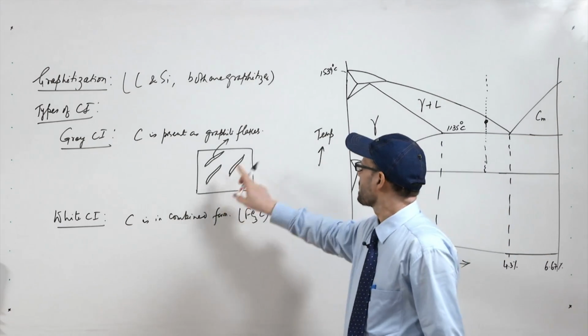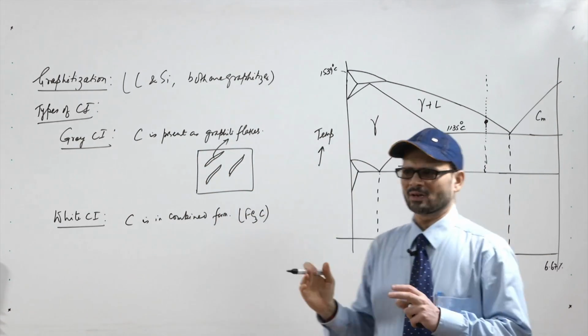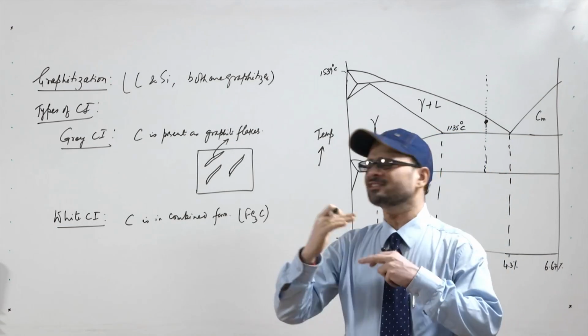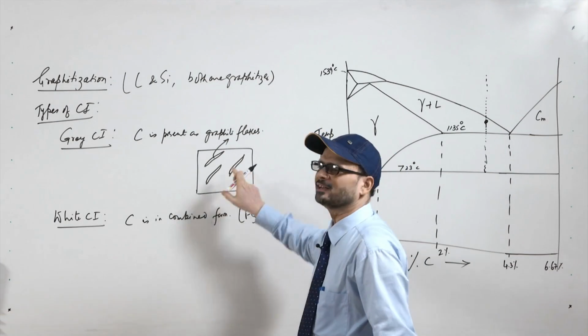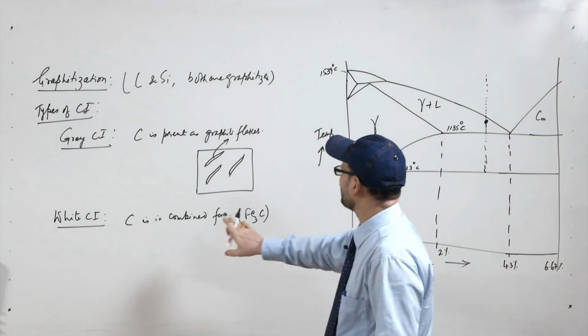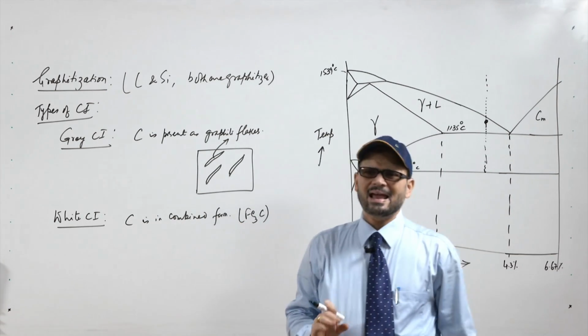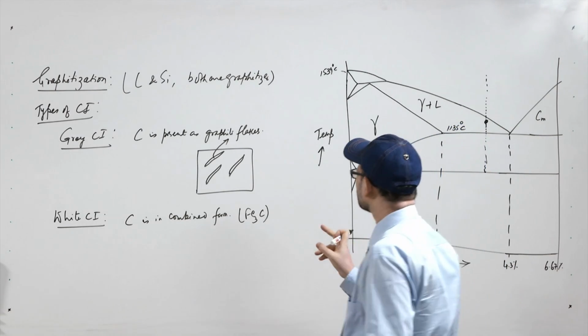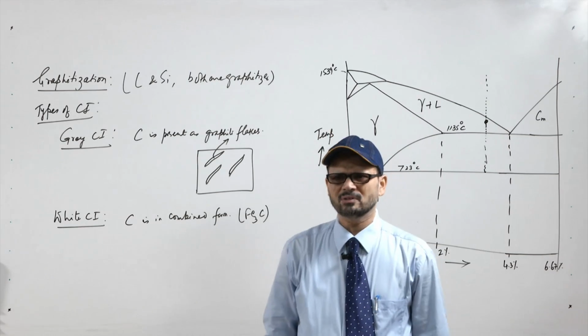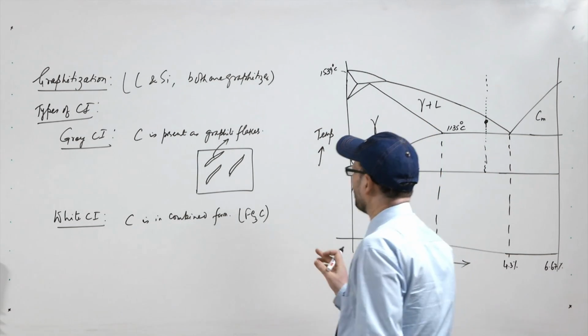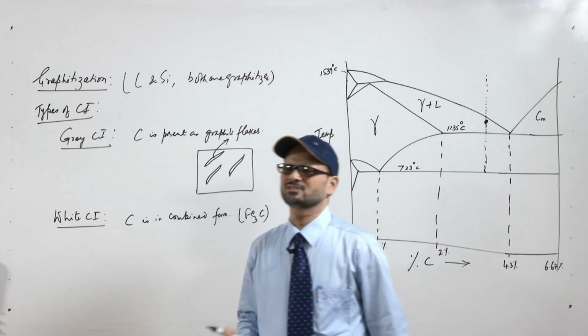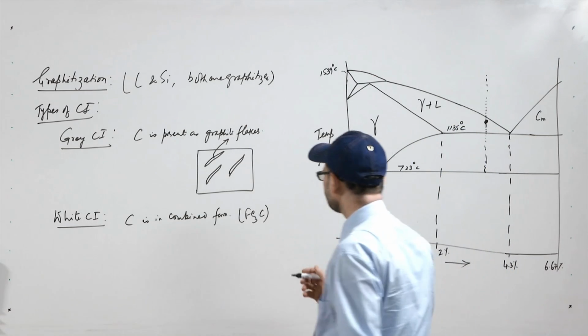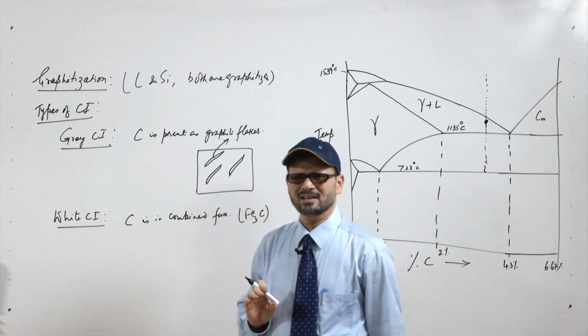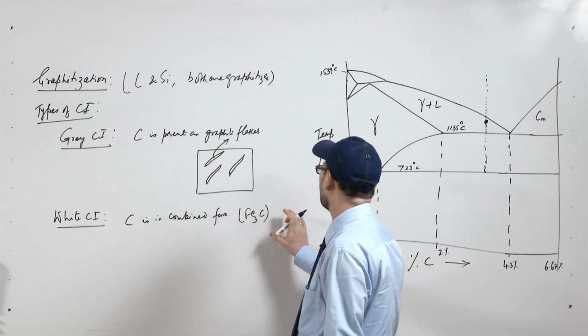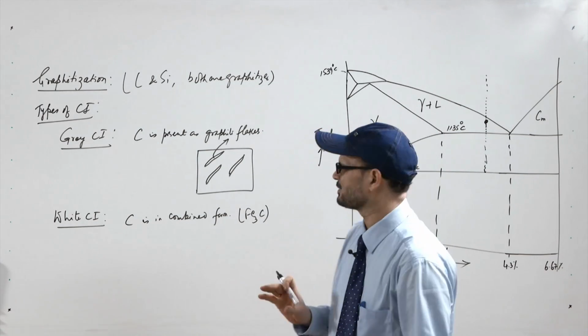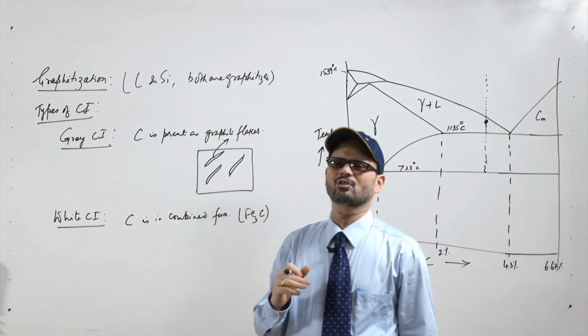So, when the carbon and silicon both are on the higher side, then when the carbon separates out, since it has a graphitizing tendency, your carbon goes in as the graphite flakes. But when the carbon is less and silicon is also less, and if the cooling rate is a little fast, then this carbon is in the form of Fe3C, that is in the form of carbide, and that is why this is known as white cast iron, and the name white appears because the fractured surface appears white. It has very high hardness, ductility is less, and mostly it is not used for engineering purposes, except where very high compressive strength is desired, like for rollers in steel plants.